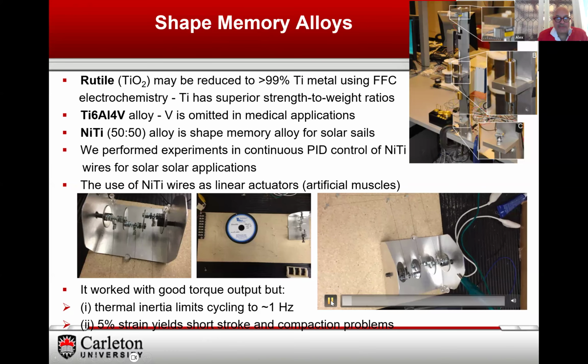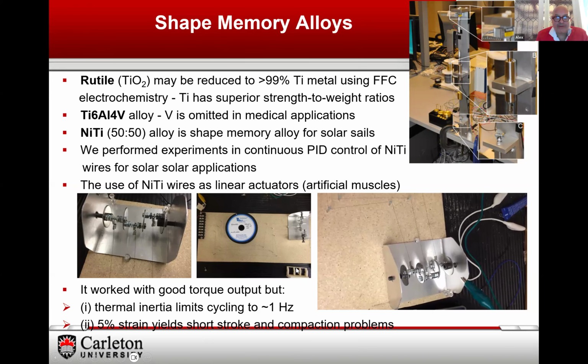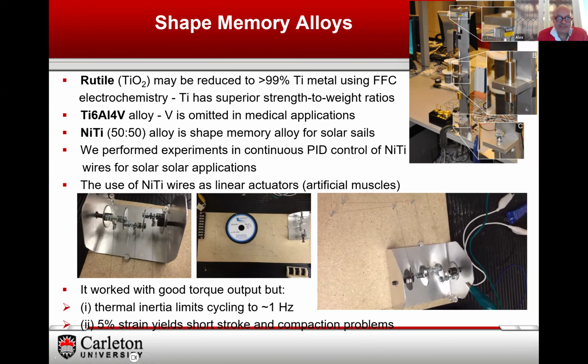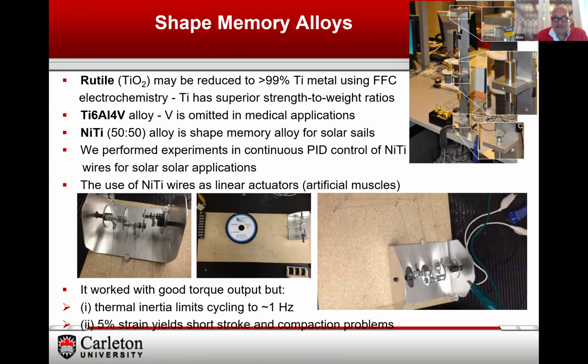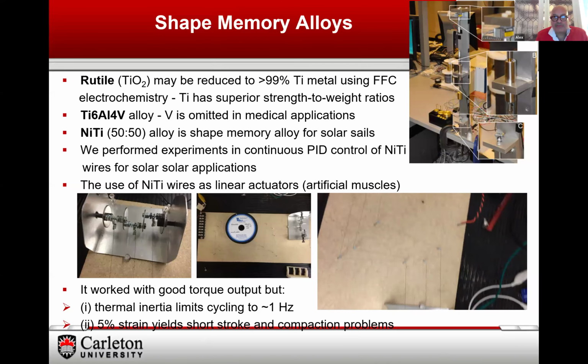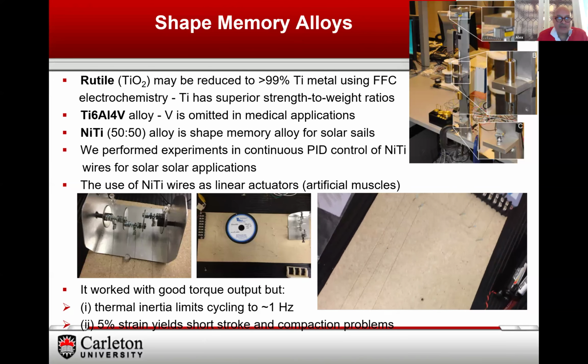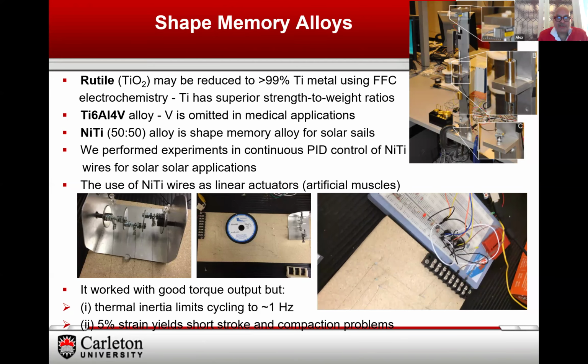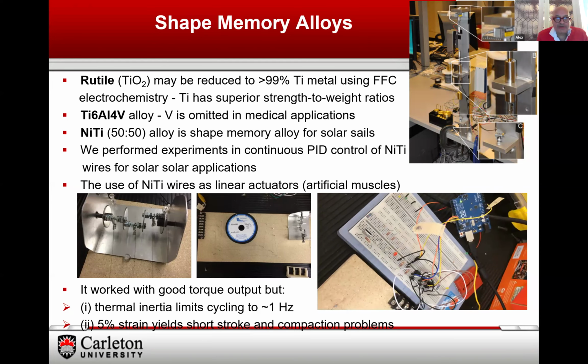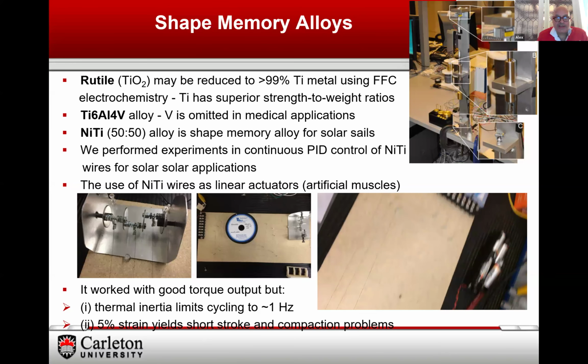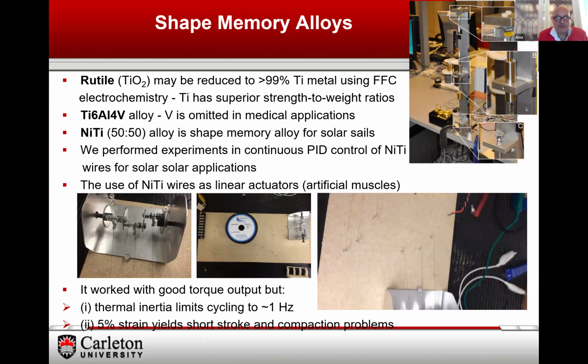Now, one of the things you'll notice here is that the wires are very, very long. This is because the strain in it is only about 5%, so you're getting an extremely short stroke. And this illustrates one of the issues you have with smart materials: you can either get good torque output or you can get good stroke, and you can't get the two together usually.